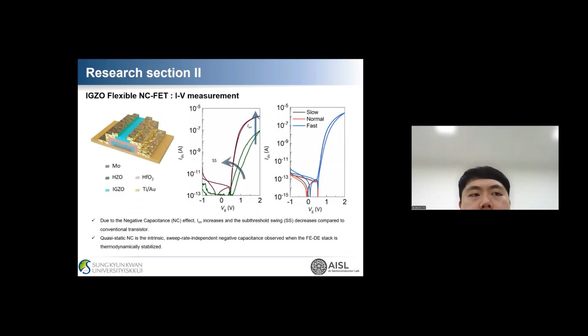After characterizing the ferroelectric property of HZO fabricated using plasma, we integrated it into an actual transistor on a polymer substrate, specifically polyimide. By inserting an additional dielectric layer in series, we achieve capacitance matching, which helps stabilize the ferroelectric behavior. We then compare this device with conventional transistors fabricated using typical dielectric such as hafnium oxide or Al2O3. As shown in the results, the capacitance-matched NCFET exhibits a higher on current and lower subthreshold swing compared to the unmatched transistor.